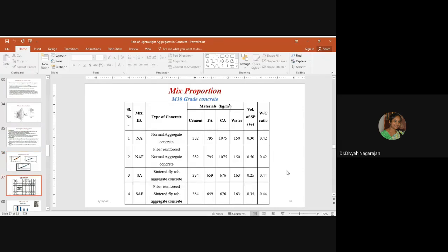Now coming to mix proportion, I have used M30 grade of concrete. The neural network is trained in such a way that the models can be used to find out the factors affecting the strength parameters of the lightweight aggregate concrete. With the lack of sufficient codal provisions on the strength properties of lightweight concrete, the mix procedures are often tedious. Therefore, the relationship between the strength properties conforms to the guidelines of mix proportioning as per IS 10262. And to some extent, the models formulated through the neural network were found to be reasonably good.